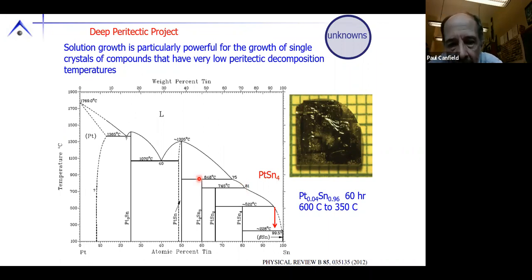So these incongruently melting compounds, these are the ones that you say are sort of hard to reach regions. And that's the whole philosophy of trying to grow platinum tin 4 or other deep peritectic materials. On the other hand, you just need to figure out where this peritectic hits the liquidus, and then you can slip it underneath it and grow the material. And as you can see here, you get beautiful crystals. So the essence of solution growth is finding where the liquidus line or surface is and intersecting just that. And that's quite an experimental difficulty all by itself.